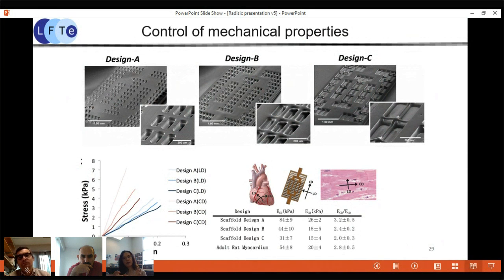But in addition to that, by tuning the lattice shape, we can tune apparent mechanical properties of this scaffold. So this is not a true Young's modulus because of the holes, but it is basically an apparent Young's modulus. And this enables you then to control anisotropy.